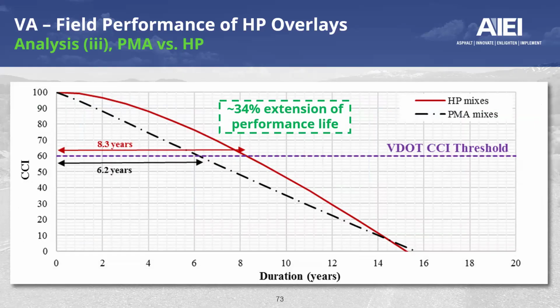compiled all critical condition index data for HP sections versus PMA, and we plotted these data as a function of the duration in years. And as expected, you expect that your CCI is going to decrease with time. So you'll see in this plot, for the red, that's the HP mix, the decrease happened at a lower rate, and you will notice a CCI of 60 is VDOT's CCI threshold.